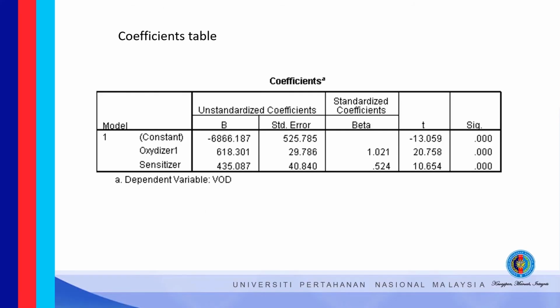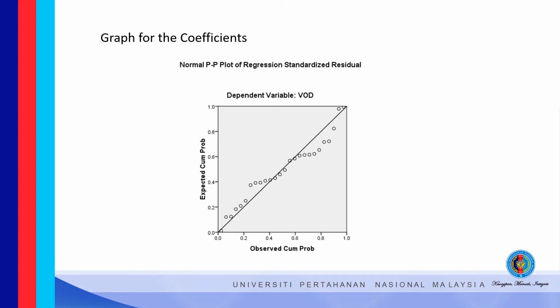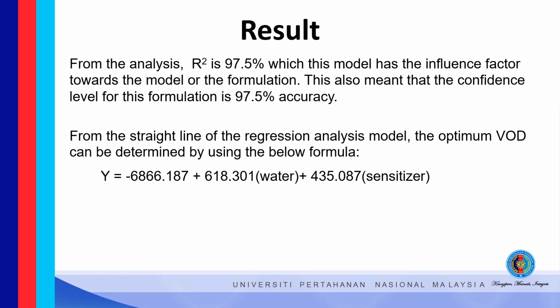So this is the coefficient table. From the coefficient table, we can get the values for the formula. From here we can see the constant is minus 6866.187, the oxidizer 1 is 618.301 and the sensitizer is 435.087. This is the graph for the coefficient that shows the close relationship between the dependent variable and independent variables. The result from the analysis, coefficient of regression R2, is 97.5%, which means this model has the influence factor towards the formulation. This means that the confidence level for this formulation is 97.5% accuracy.